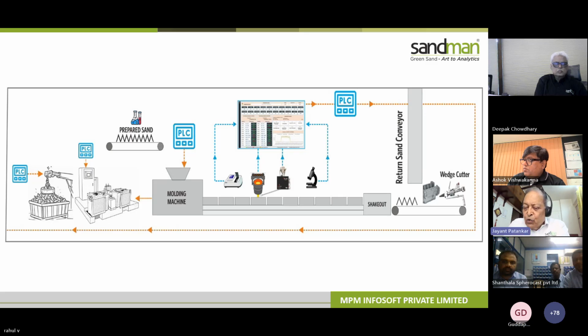Uniform hardness is an issue in a casting. If the casting is thin walled as well as with thick bosses, expecting uniform hardness in a thin section as well as a boss section is not practical. The reason any specification gives a range, say an FG200 grade requires a hardness of 182 to 206 or 210, is the wall thickness range. The thickness is 12 mm to 50 mm.